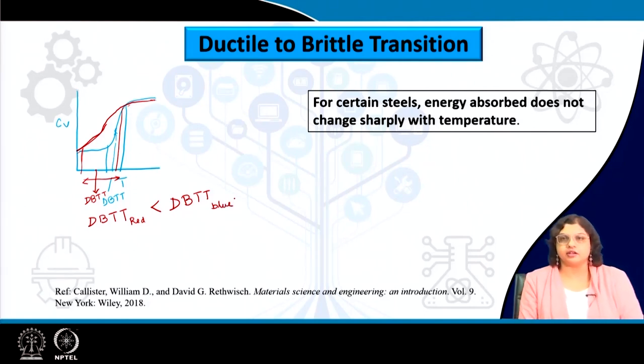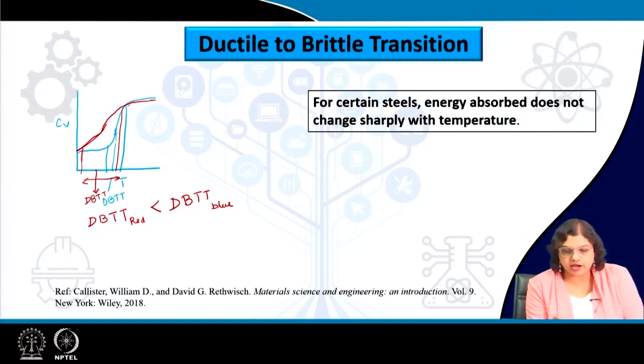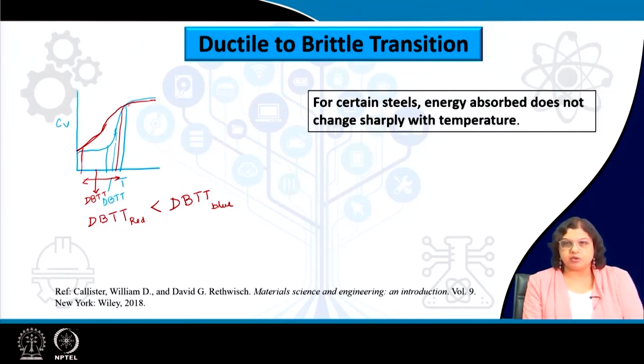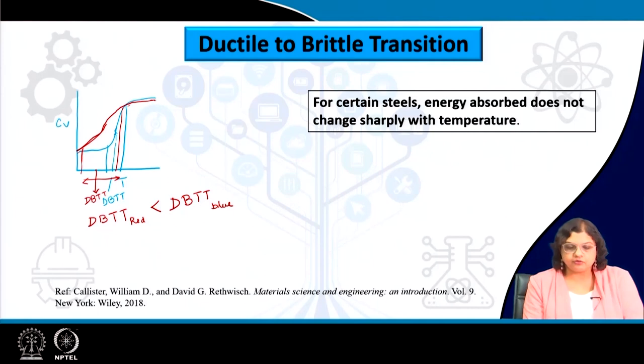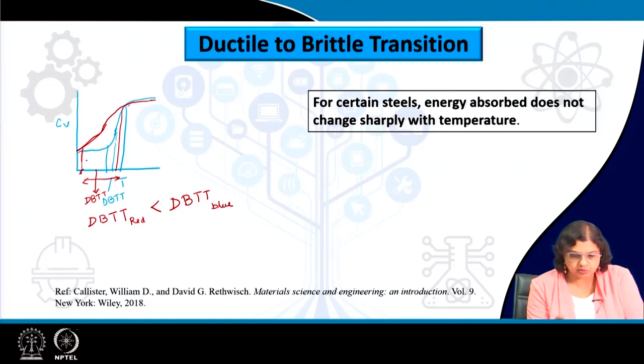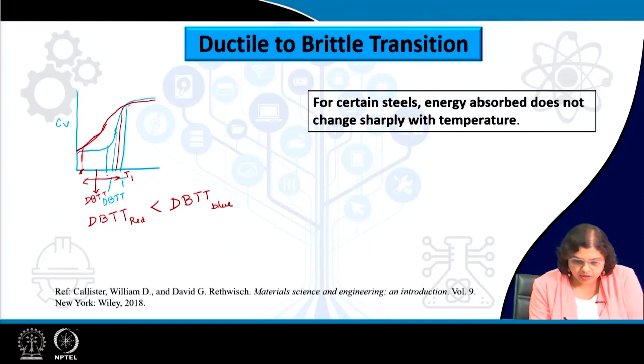This also gives us a dilemma when selecting a material for service. Although both materials might show similar fracture behavior or similar toughness at room temperature, at service temperature they may behave differently depending on the exact temperature. If used at a very low temperature T2, both materials would show a brittle failure mode.